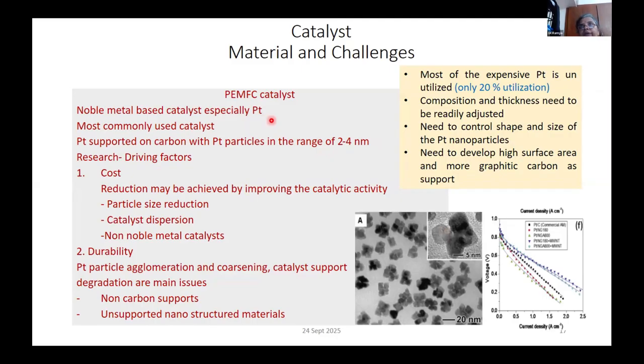we have two different atmospheres actually. First, it is an acidic environment. Second, you have hydrogen, which is highly reducing, and on the other side oxygen, which is highly oxidizing. For that kind of catalyst, platinum is the best, because it is stable. You don't see platinum getting oxidized. And if you look at the volcano plot, platinum has the highest activity for these kinds of reactions. So that is the most commonly used catalyst.